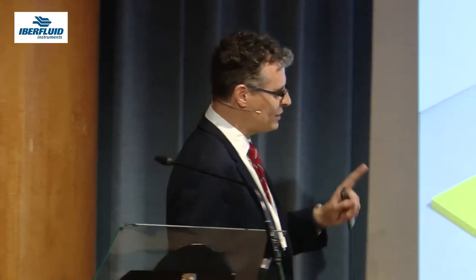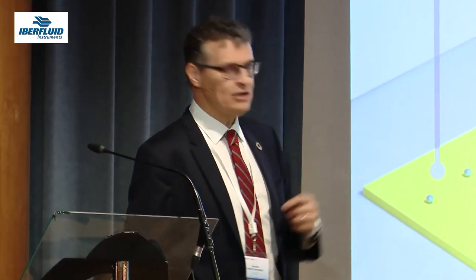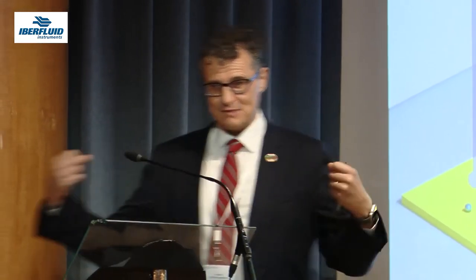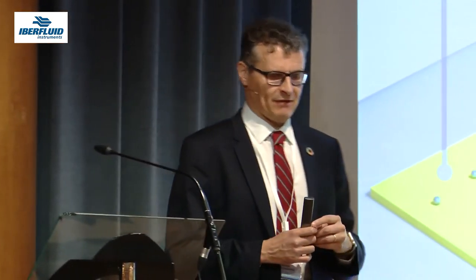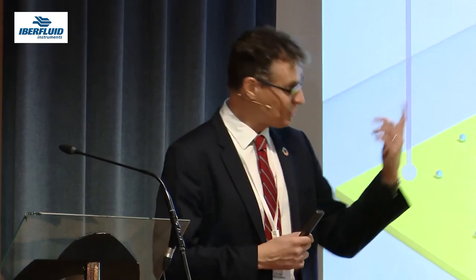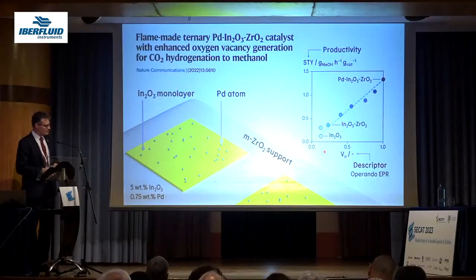And because indium oxide is quite lazy in splitting hydrogen, we need to add a promoter to facilitate hydrogen splitting. And that promoter is palladium here, but it has to be atomic. It's good that it is atomic. If it is nanoparticle, it will catalyze the reverse water gas shift, so you will produce more CO, you will lose selectivity to methanol. And as we work in catalysis, we try to find a descriptor that correlates your performance, the space-time yield, with your property.